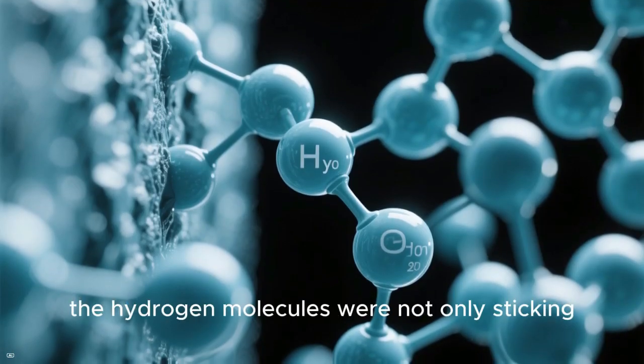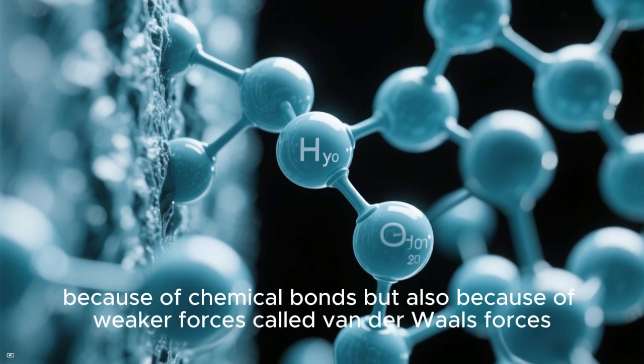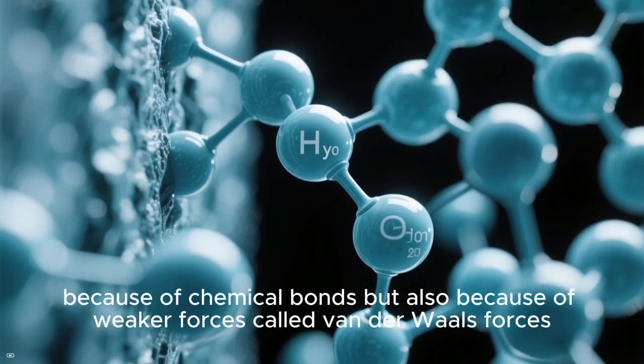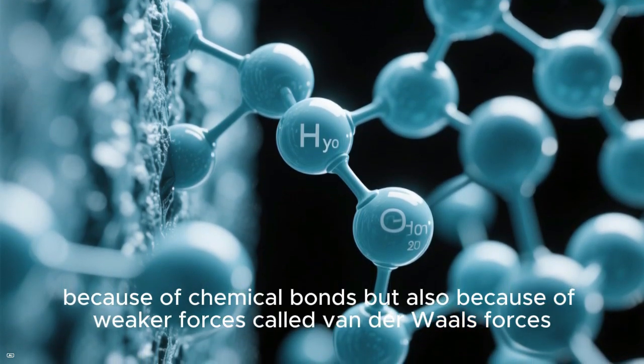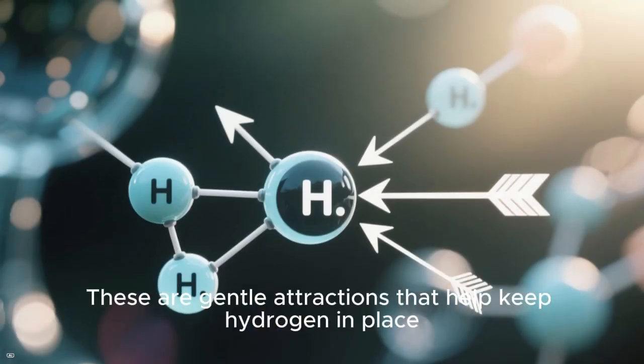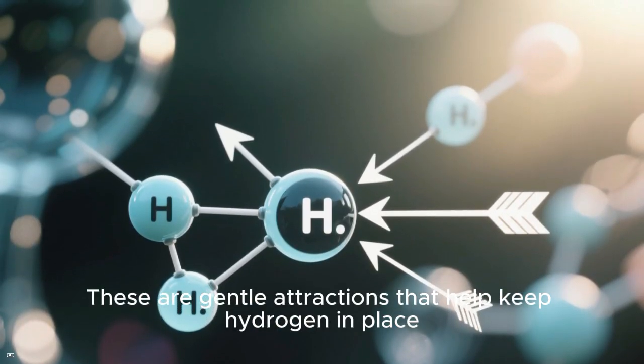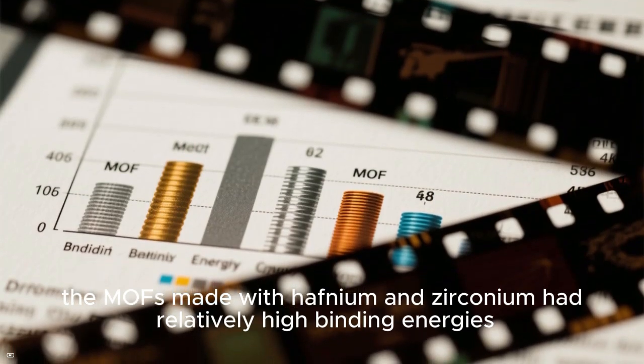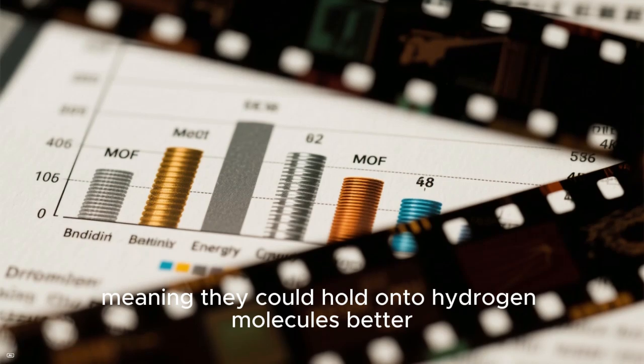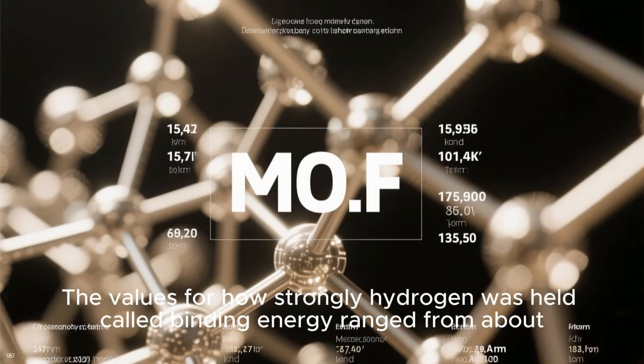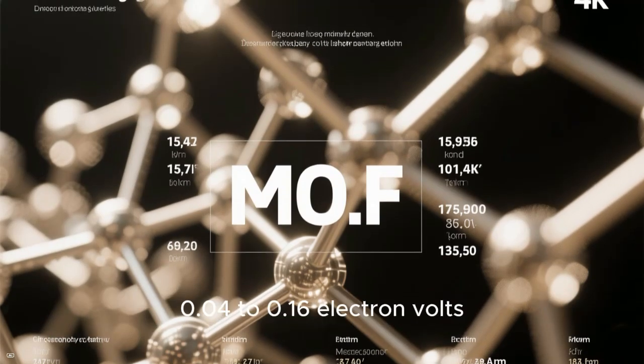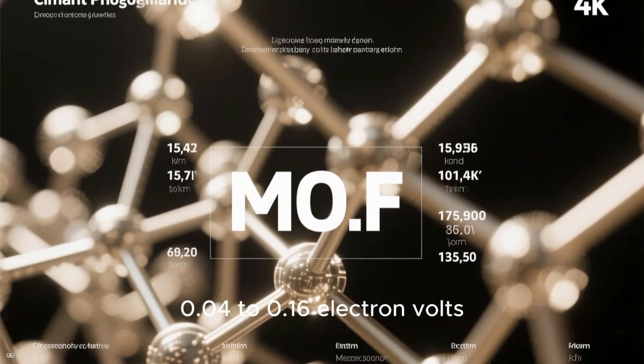Interestingly, the hydrogen molecules were not only sticking because of chemical bonds, but also because of weaker forces called van der Waals forces. These are gentle attractions that help keep hydrogen in place. In particular, the MOFs made with hafnium and zirconium had relatively high binding energies, meaning they could hold onto hydrogen molecules better. The values for how strongly hydrogen was held, called binding energy, ranged from about 0.04 to 0.16 electron volts, depending on the metal.